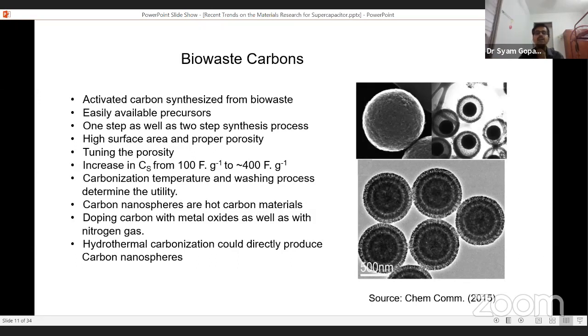In this bio-waste carbon itself, carbon nanospheres are now the hot carbon materials for supercapacitor application, owing to their appropriate pore size for electrolyte intercalation. Then another line of research going on in this bio-waste carbon is doping carbon with metal oxides, so that some pseudo-capacitive property can be combined with this EDLC material, so that its energy density can be increased without much loss in its power density. Then one more technique for synthesizing bio-waste carbons is hydrothermal carbonization, which can directly produce carbon nanospheres.